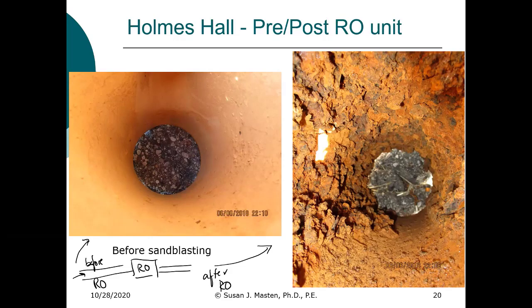So what's happening here? Basically corrosion. These are referred to as tubercles. What is happening is you produce a water that has almost no mineral content to it. As a result, any oxygen in that water, if there is a disinfectant in that water, is able to come in contact with the raw metal. That results in a significant amount of oxidation of the metal itself, and you end up with an iron pipe with these types of tubercle formations. If these break off, they're very brittle, and if they break off, then you end up with red water incidents in the system.